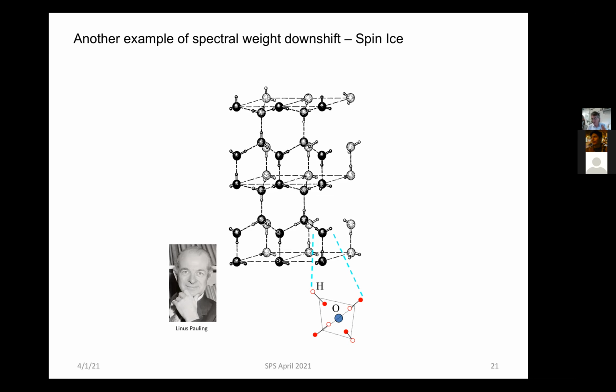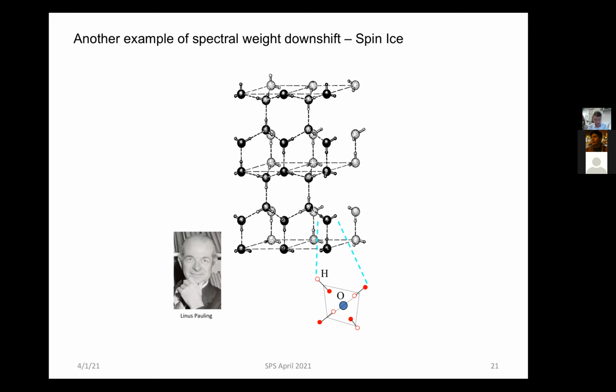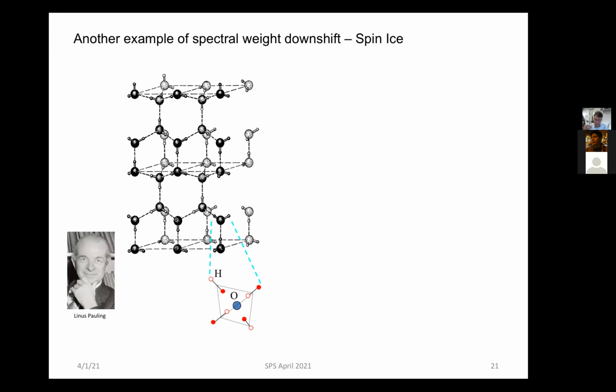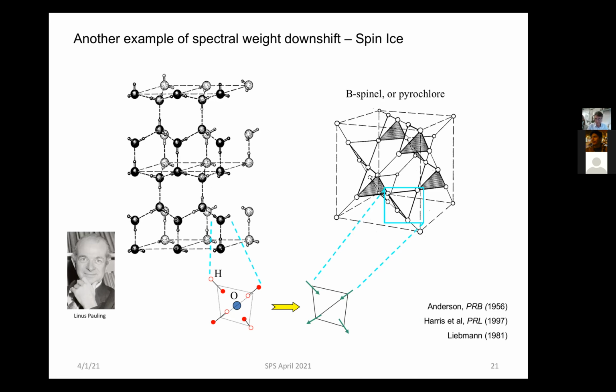And Linus Pauling, the very famous chemist who won a Nobel Prize for chemistry, but also a Nobel Prize for peace, showed that this discrepancy in the entropy can be explained by stipulating that the hydrogen, so this is a picture of ice, this is what's in your freezer. Ice is a material where the lattice is ordered. So all the oxygens live on a perfectly ordered lattice, but the hydrogens are completely disordered. They can't break the H2O bond, but the H2O orientation can be in 6 different ways on every oxygen atom. And that gets frozen into the system at low temperatures, such that you have this ground state entropy.